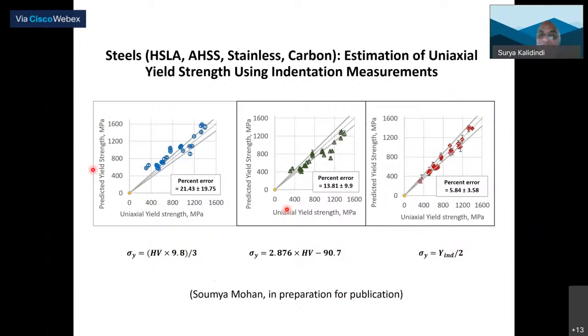This is along the same lines, but this time we wanted to know what is the error in just the estimation of the yield point, not the entire stress strain curve, but just the yield point. And we are showing that these techniques are much more accurate than the current techniques that people are using to convert hardness into yield strength. And again, keep in mind the range is very large, from this end to that end. We are covering a very large range of yield strengths, and we are still getting pretty good answers.